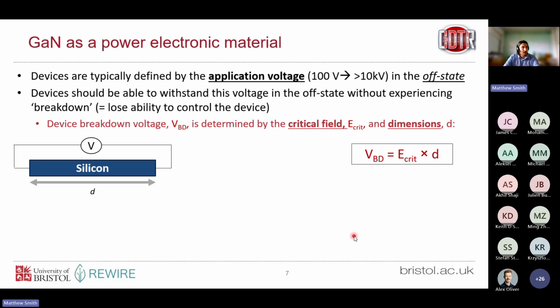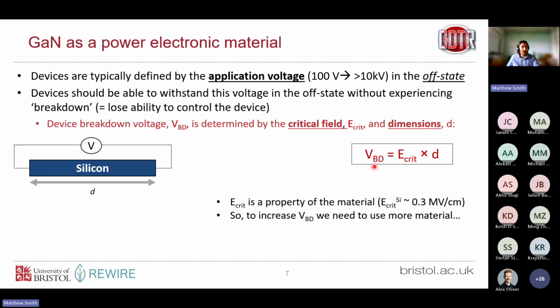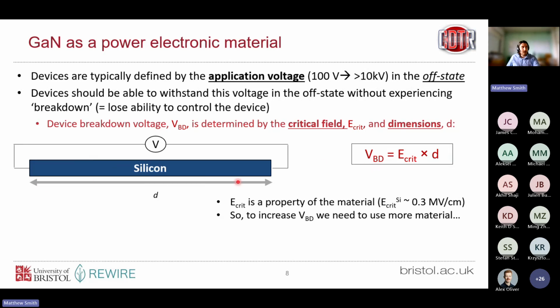So, okay, why gallium nitride then? That's kind of setting the scene for power devices, but why GaN? Well, I mentioned we've got this application voltage, so a device will have to withstand a certain voltage in one of these power converters, and we can define the breakdown voltage, which is how much voltage we can apply before the semiconductor material in our device breaks down. Very crudely, we've got this model here where the breakdown voltage is defined by the dimensions, so the length over which we're applying voltage, and this property, the critical electric field of the material. So we can increase our breakdown voltage by increasing this value D here. So we've now got a greater distance over which we're dropping the voltage.